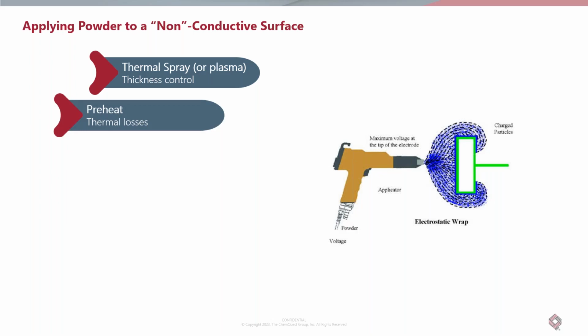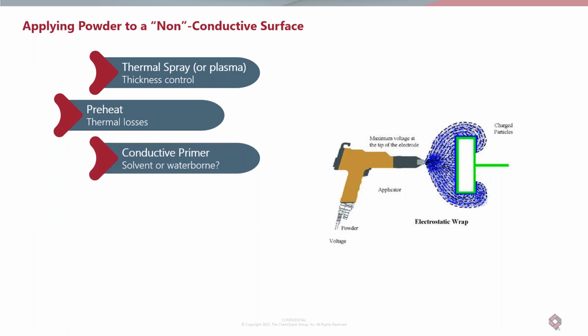Another way of doing it is to preheat the part and then spray. It's called flocking: spraying the powder onto a hot surface, where the powder will melt, fuse, and flow. The problem is that if you don't have good control over the thermal process, you may have thermal losses in certain areas on the part, and it may make the application inconsistent.